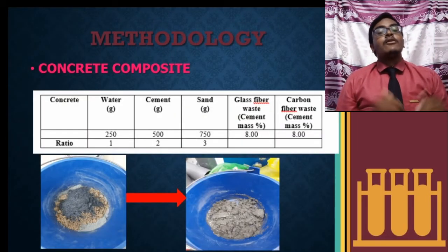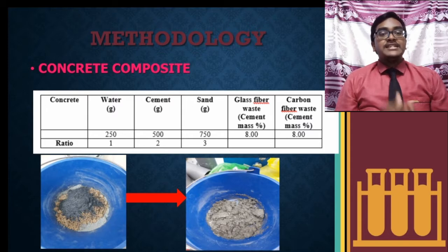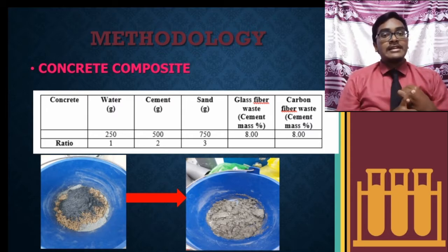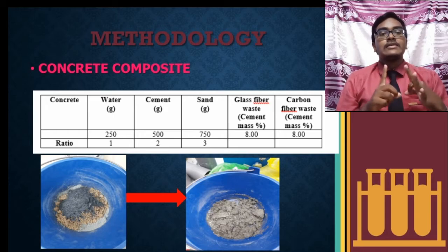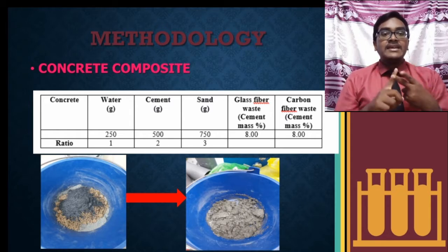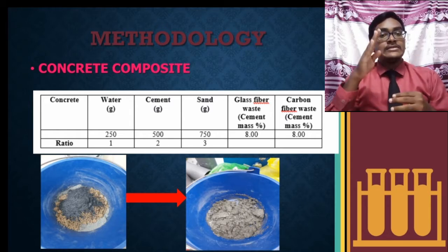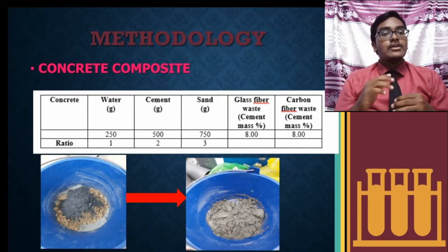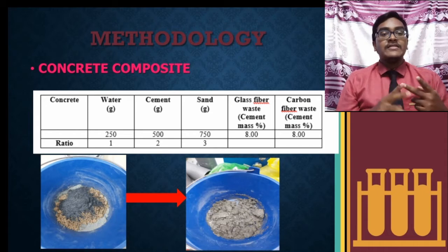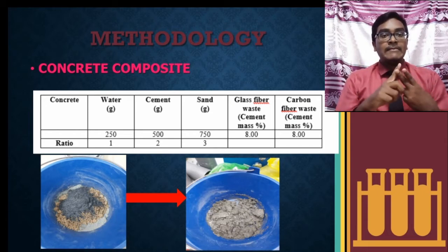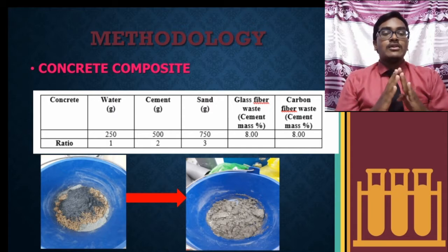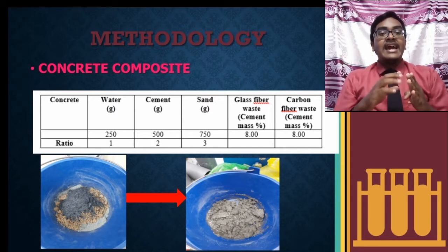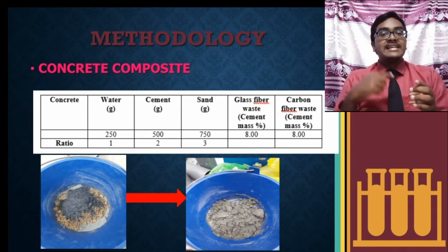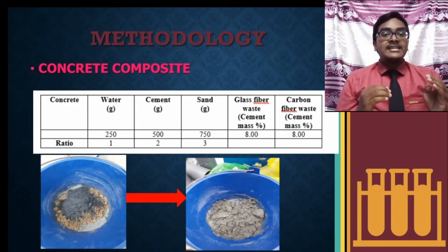Okay, now we move to concrete composite. First of all, prepare 3 containers to produce normal concrete, concrete with recycled glass fiber, and concrete with recycled carbon fiber. For normal concrete, mix water, cement and sand with the ratio of 1:2:3. Besides, for concrete with recycled carbon fiber and concrete with recycled glass fiber, mix water, cement and sand with the same ratio of 1:2:3 and then add 8% of recycled carbon fibers and recycled glass fibers in relation to cement mass as shown in the table.